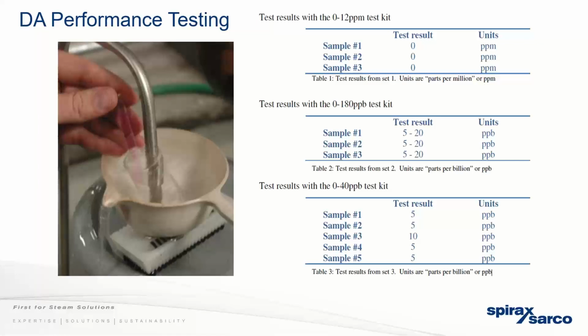So they start with a 0 to 12 ppm test kit. It should technically show 0. If you're getting values there in a deaerator, then your deaerator is worse than any tank. Then you test with a 0 to 180 ppb test kit. They'll get a range like 5 to 20, and for a good deaerator, that's where it should be. I've seen deaerators which even go up to 50, so that would not be a good deaerator. Then you would test it with a 0 to 40 ppb test kit, and you would see the actual low values. So these are actually real results.